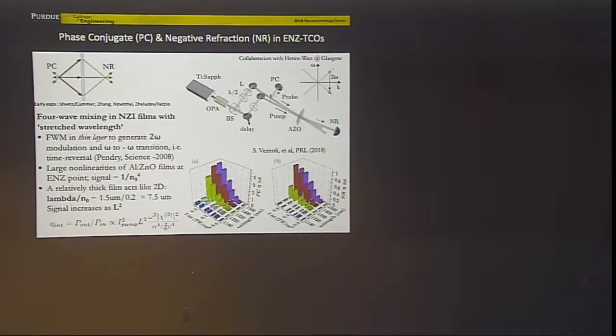We also demonstrated this for other effects, not only for the Kerr effect. In this case, it's so-called time reversal, which is kind of interesting physics. It was first suggested by John Pendry from Imperial College, who said if you take a very thin layer of material where the electric permittivity is modulated at frequency 2 omega through a nonlinear process, and a beam at frequency omega is incident on such a material modulated at 2 omega, then because of